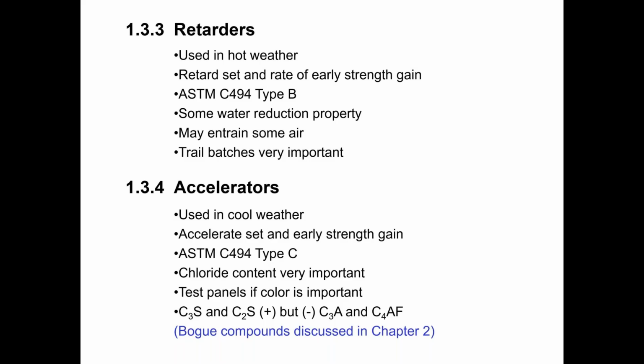So generally the C3S is going to be a primary contributor to the early strength gain of the concrete. The C2S also contributes, but not as much as the C3S. And so accelerators generally help to speed up the reaction of the C3S and C2S oxides. On the other hand, they generally slow down the reaction of the C3A and the C4AF. And we'll be talking about these oxide compounds in just a few minutes when we get into chapter 2. So these are referred to as Bogue compounds. And in chapter 2, we'll talk about how these oxides are calculated, how they're derived, and what these different oxides do as far as the physical performance of the cement.